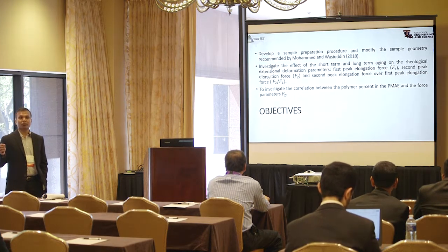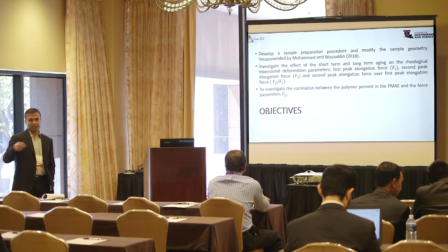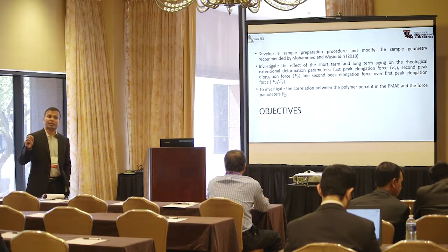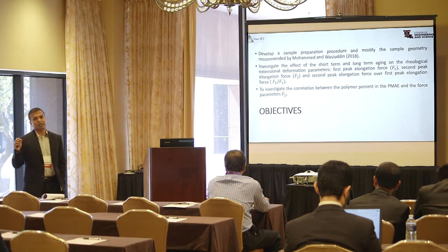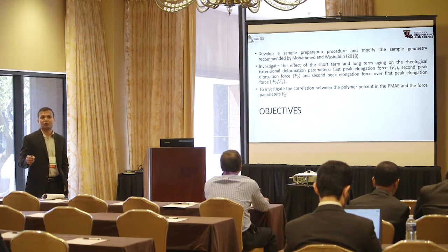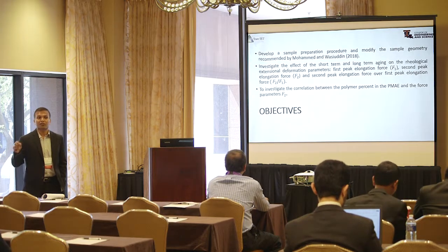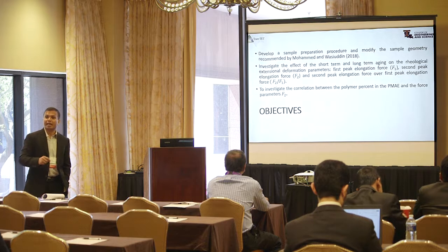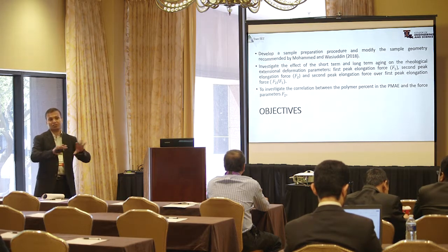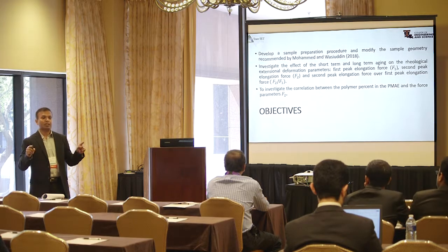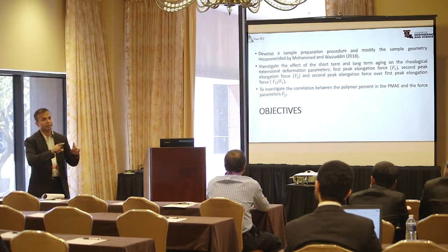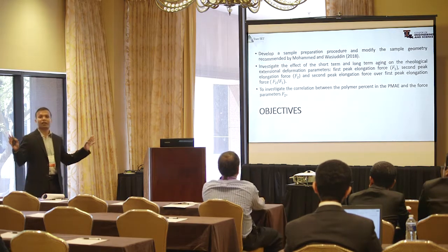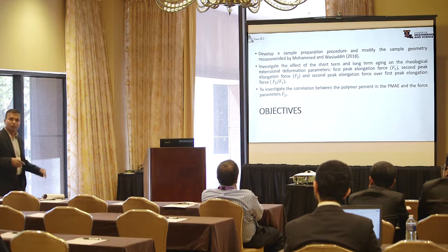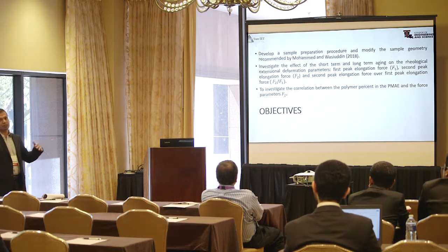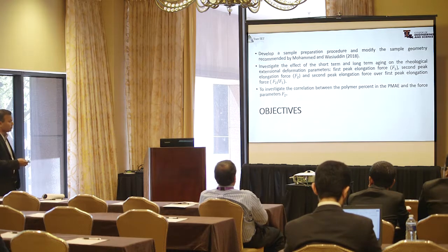So we did that, and we were very close, and our new specification is actually MSCR based in Louisiana, the proposed new one for replacing elastic recovery. But that was a 3-year project, and we found no good correlation between the force ductility parameters and any of the shear deformation. So force ductility doesn't connect to the DSR properties, whereas the elastic recovery really connects to MSCR very well. And several other state agencies, DOTs, did research almost at the same time in the last 5 to 10 years.